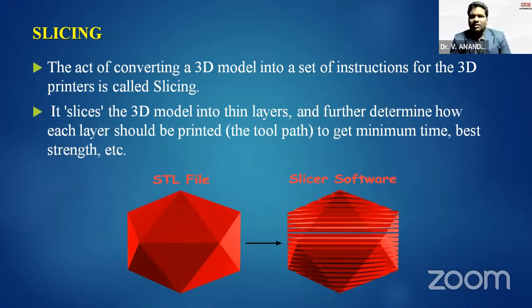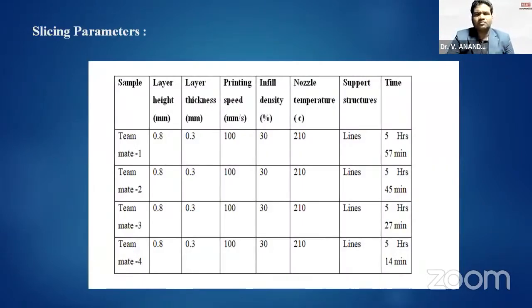Slicing is a main important parameter to get a high resolution component, or to get the fine details of the component. In their project work, they prepared their 3D models in the Blender software, and they set layer height 0.8, layer thickness 0.3, printing speed 100, infill density 30, that is 30% of the material only set in the model, nozzle temperature 210 degrees centigrade, and support structures as lines. As we discussed, if we set the support structure pattern as lines, we can remove the material with less effort, and damage to the main product can be avoided.